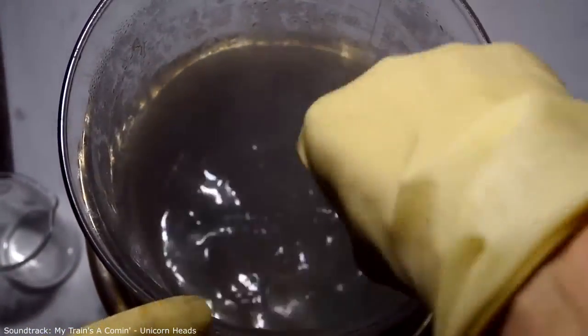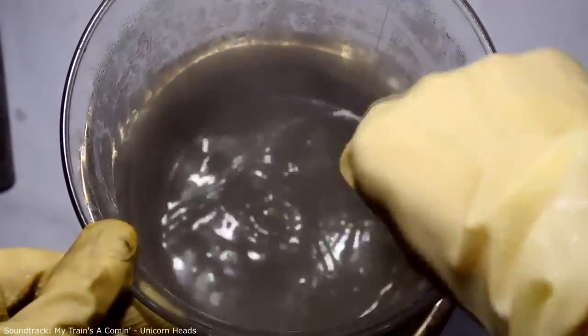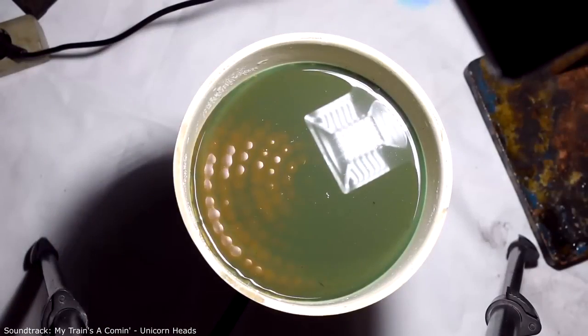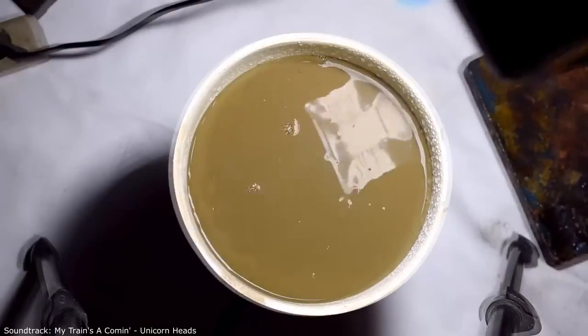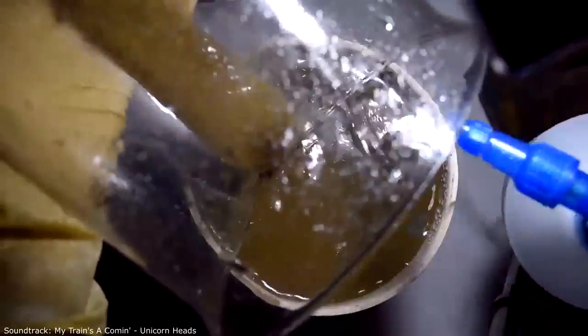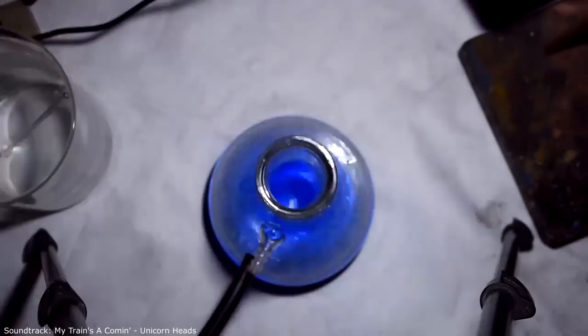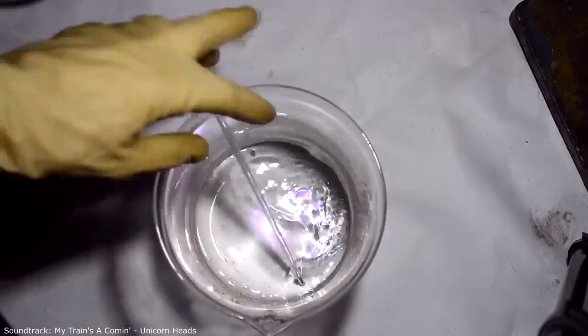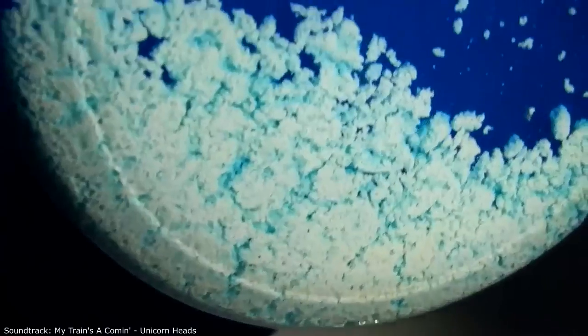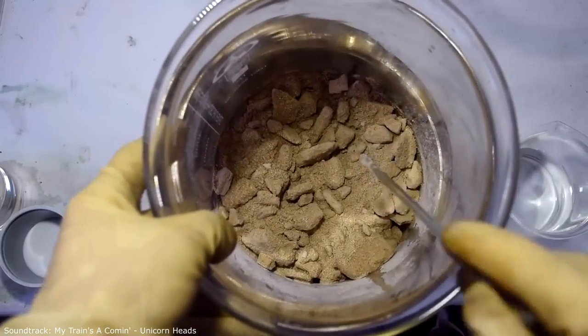After a while, the release of brown gas stopped. We check by pouring in a little more nitric acid — if there is no reaction, the copper and silver leaching process is finished. Copper is clearly present; let's see if there is silver. A decent amount of silver chloride settled to the bottom of the 3-liter glass. The material from the funnel dried up; I poured it into a 5-liter glass. Now we need to do the leaching of the golden hairs.